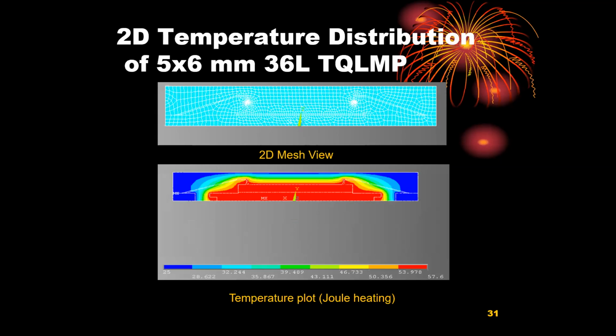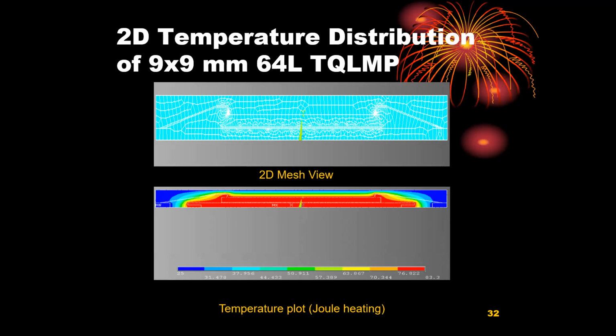So the various maximum operating temperatures, in a fully transient or a steady state analysis, had to be found out first through simulation, and we could also check how good the simulation was when we did the test with unencapsulated and encapsulated ICs. So sometimes we get maximum operating temperatures that are threateningly close to the glass transition temperature. I'll come to that later.